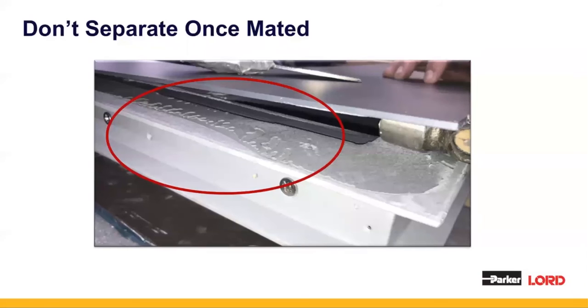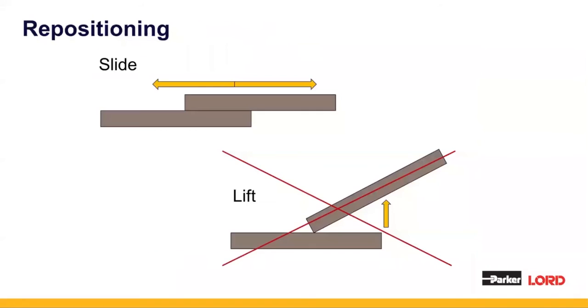So if you do see this air entrapment, what you're going to have to do is completely start from scratch. That means taking apart your parts, cleaning off the adhesive, and beginning the bonding and assembly process all over again. Now, if you need to reposition your parts, it's best to do this by sliding, not by lifting. Lord acrylic adhesives are equipped with glass beads, which help to enable sliding for repositioning. But if the parts do come apart, or if you simply need to rework the assembly, just scrape off the adhesive, clean with an alcohol wipe, and then start the process again.